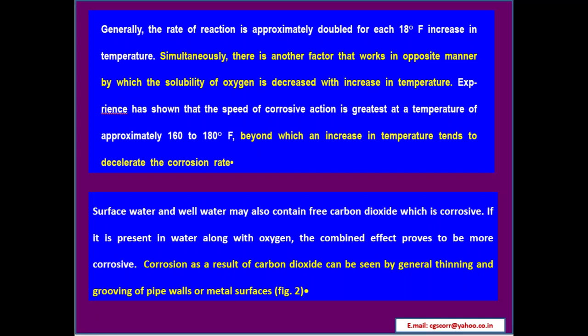Surface water and well water may also contain free carbon dioxide, which is corrosive. If it is present in water along with oxygen, the combined effect proves to be more corrosive. Corrosion as a result of carbon dioxide can be seen by general thinning and grooving of pipe walls and metal surfaces.